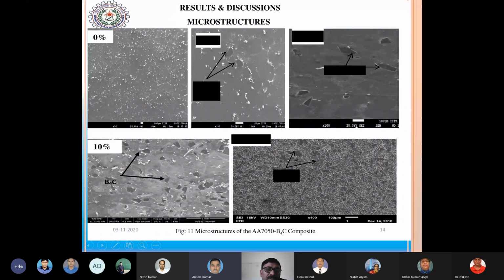So the distribution supports it, but further, if many more distributions are there, such as titanium carbide particles, boron carbides, or other nitrides, then your strength will obviously be improved. As you know, as per the Hall-Petch equation, as and when the grain size gets smaller, the strength gets better. So this is the correlation of the microstructure with the mechanical properties.